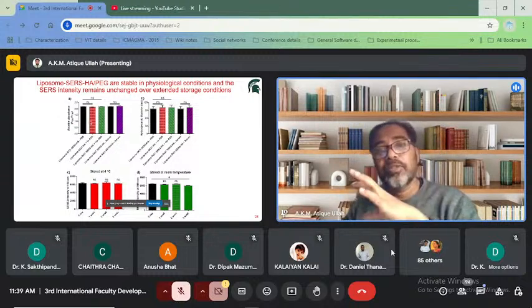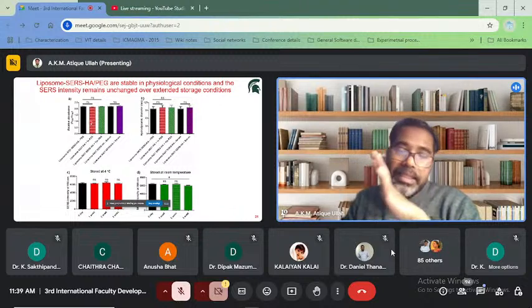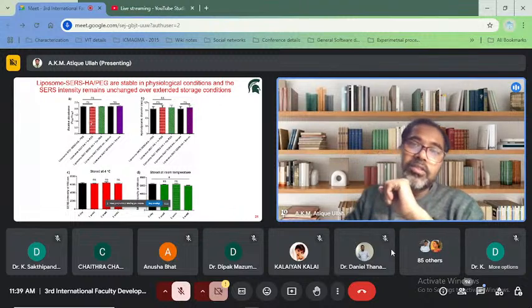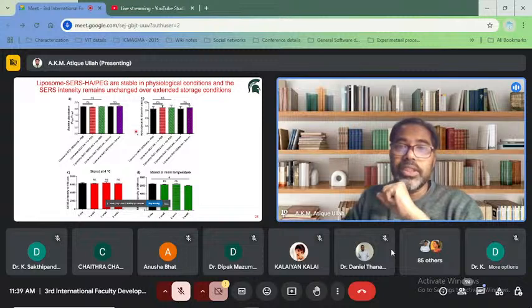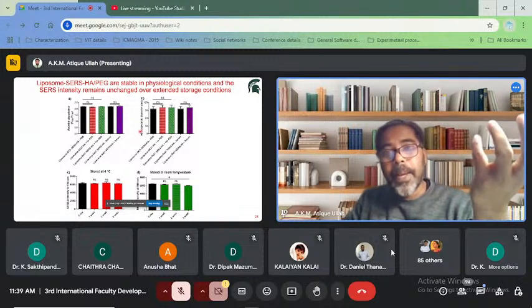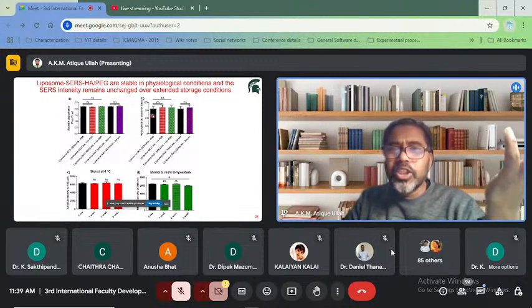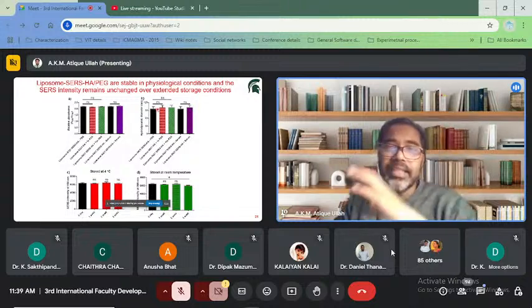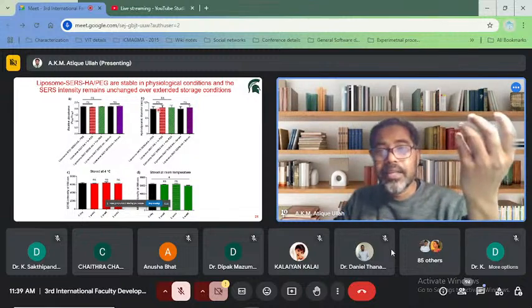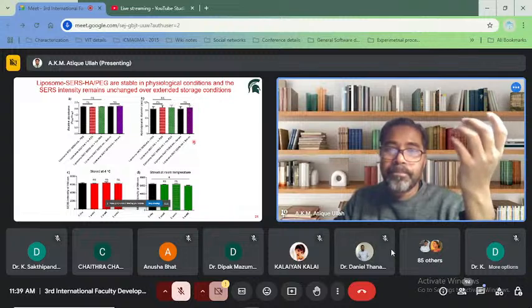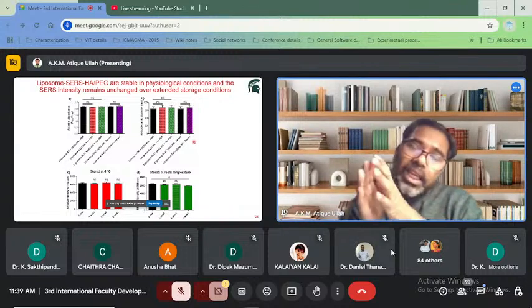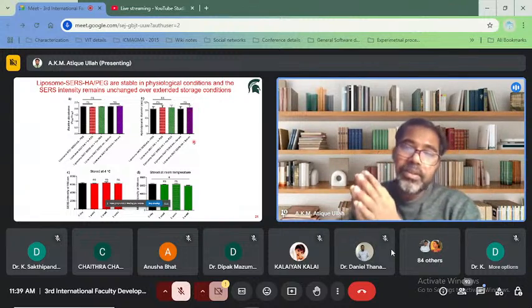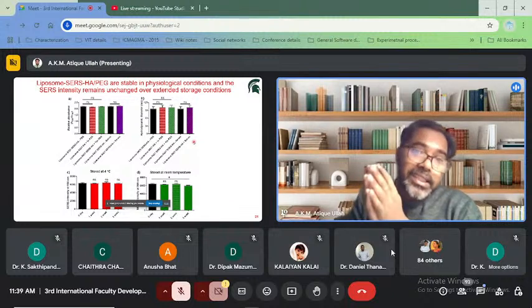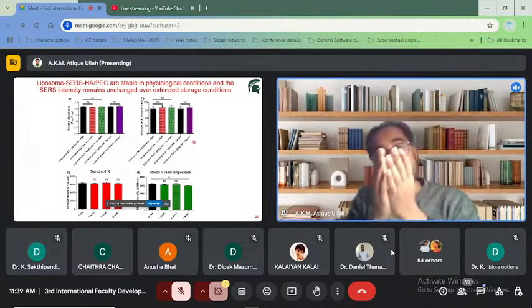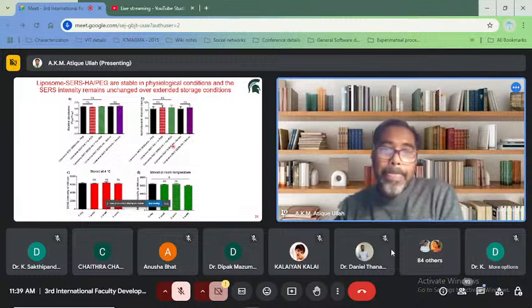We further confirmed the stability of our SERS nanoparticles under physiological conditions through the hydrodynamic diameter. You can see there is no significant change in the hydrodynamic diameter in PBS and serum. That means our SERS nanoparticles are stable in the physiological conditions we examined, in PBS and serum.